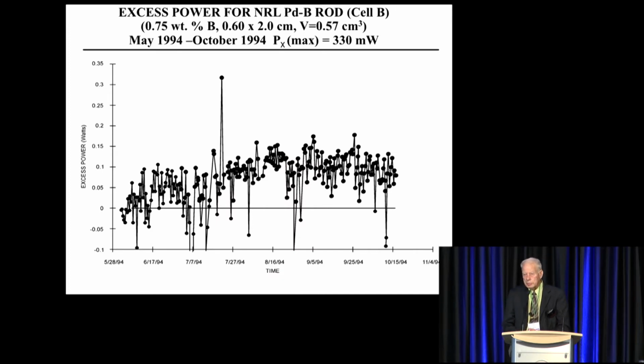The Navy program started in 1992, and NRL was making materials like pure palladium, palladium silver, palladium cerium, but it was very frustrating because nothing produced excess heat. In 2 years, I understand people getting frustrated because that was very frustrating. Sometimes I'd go to other material just to see if I could get the effect still. But in May of 1994, we did get excess heat. The first experiment I tried with palladium-boron gave excess heat.